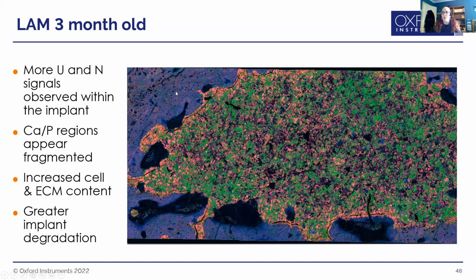And here you've got the bone. So clearly we can see the difference between the bone and the implant material. And you can see some areas where the implant material actually doesn't follow this crack line. You can see the differentiation much better with the EDS than you could with the backscattered data. So hopefully that's given you a bit of an idea.